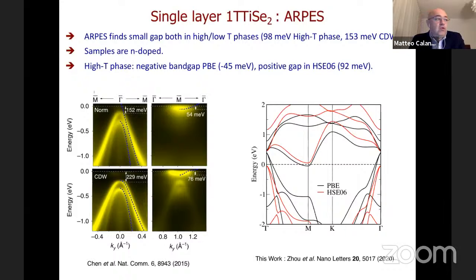However, you can also do the same using density functional theory plus U. But if you do density functional theory plus U, you lose the charge density wave instability, because the bands turn out to be correct, but not the vibrational properties. The gap in HSE06 is almost perfect. The gap between gamma and M is 92 millivolt against 98. I think it's too perfect.